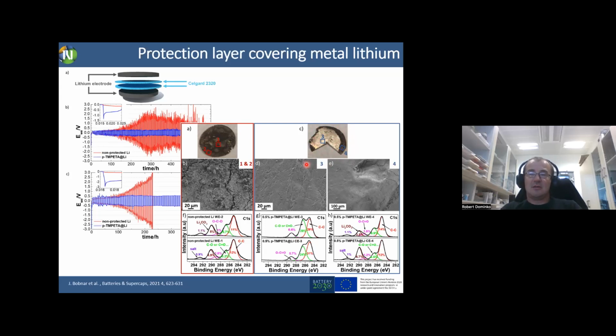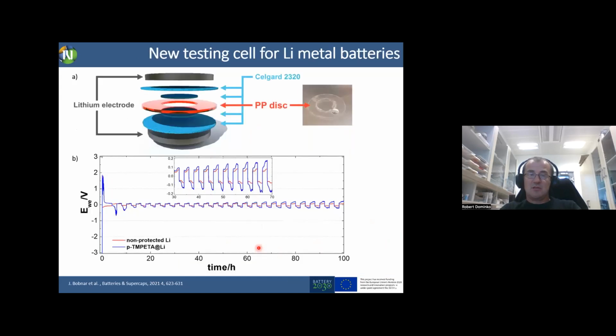And that's a clear signal, okay, the area that was covered with TMPETA was not electrochemically active because there was too high resistance, or slightly increased resistance on that area, and that correlates all the electrochemistry to the edge. That was then covered by SEM and also by XPS, but I don't have time to go deeper into this. So that was giving us a hint: if you want to study this and have reliable studies, we need to design a cell which can protect edges, and where edges are not active, since we know that sometimes it's very hard to protect edges also with this protective layer.